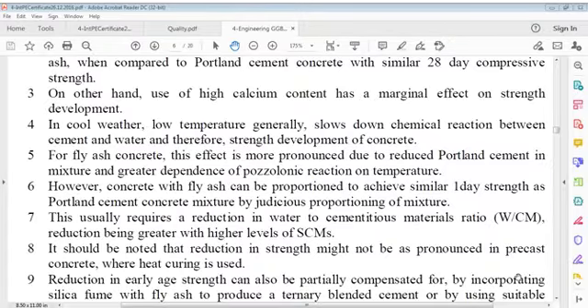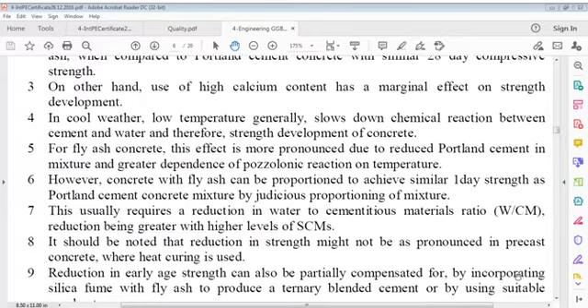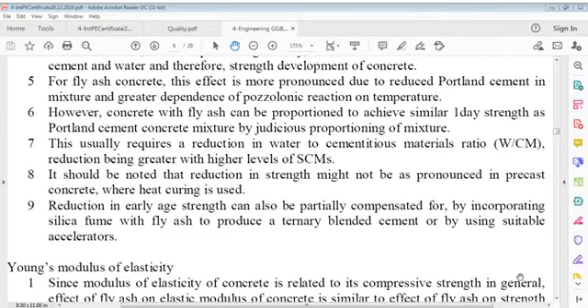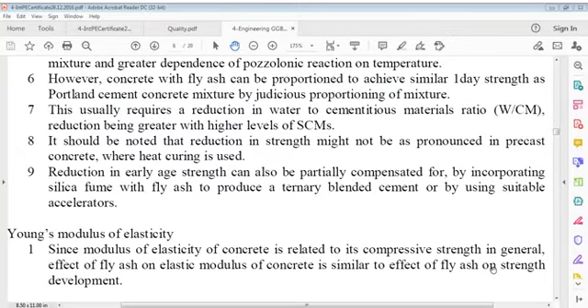In cool weather, low temperature generally slows down chemical reaction between cement and water and therefore strength development of concrete. For fly ash concrete, this effect is more pronounced due to reduced Portland cement in the mixture and greater dependence of pozzolanic reaction on temperature. However, concrete with fly ash can be proportioned to achieve similar one-day strength as Portland cement concrete mixture by judicious proportioning of the mixture. This usually requires a reduction in water to cementitious materials ratio, that is w/cm, a reduction being greater with high level of supplementary cementing materials. It should be noted that reduction in strength might not be as pronounced in precast concrete where heat curing is used.